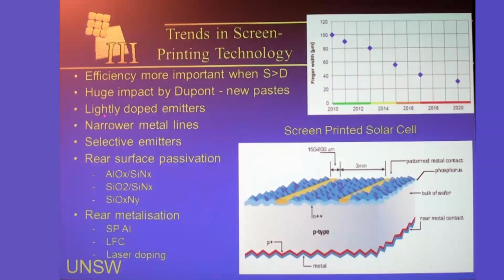And that's mainly the shorter wavelengths of light that get lost as a result of that, because they're the ones absorbed right at the top surface. But now that DuPont has developed pastes able to contact much more lightly doped emitters, a lot of that has changed. And similarly, the newer pastes are able to be printed in a much more narrow configuration than the older pastes as well. So they're able to get a much better aspect ratio.